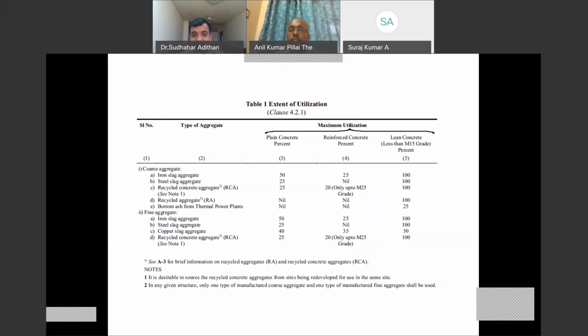If you are using it in plain concrete, it is a little bit liberal. Lean concrete, it is almost liberal, less than M15 grade. So for PCC and all, you can use even 100%, because they are only used as temporary beddings, etc. They don't structurally participate. But when you are using it structurally, or if the plain concrete itself is an integral part of the building system, for example a flooring system, then you will have to adhere to the following limitations. For each kind of aggregate, they have given an upper limit for the replacement level. Please take note of it. It is table number 1 of IS 383.